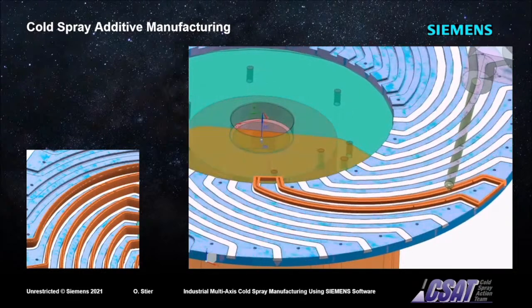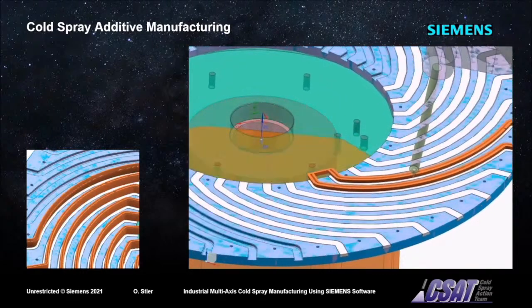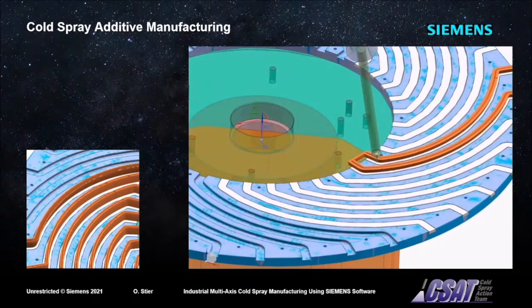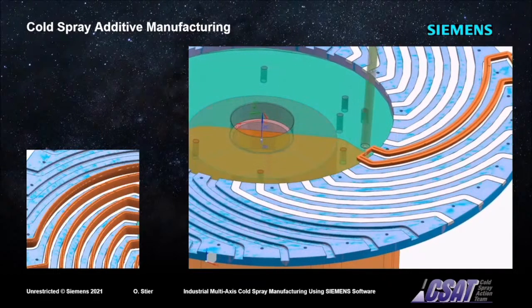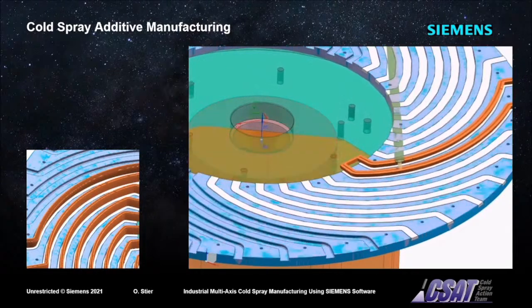Frequent repetition of the shown motion pattern makes the rails grow in height. Hereby, they form vertical walls with a flat top. The resulting cross-section shape is rectangular, with slightly rounded corners and an aspect ratio greater than unity.